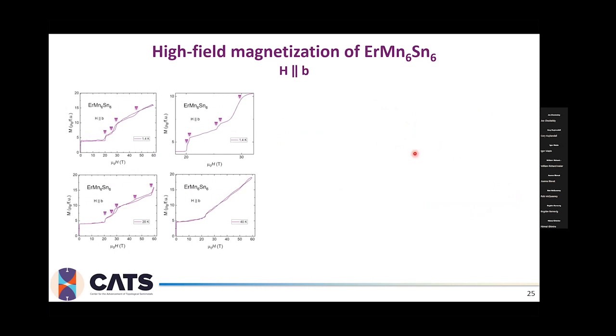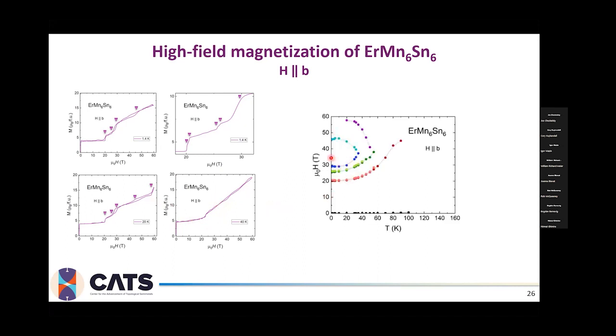When we move towards the B direction, which is very different from the A, I zoomed in on the part between 20 and 30 Tesla to show that each of those transitions actually splits into a little double transition, with a bit of structure inside. The interesting thing is that when we go higher in temperature, at 20 Kelvin, there is one more transition popping out right at the limit of our magnet, at 57 Tesla. And again, at higher temperature, it just gets smeared out. So over here, we again see a bubble inside the other bubble, but nothing is really happening in that direction in the low magnetic field region.